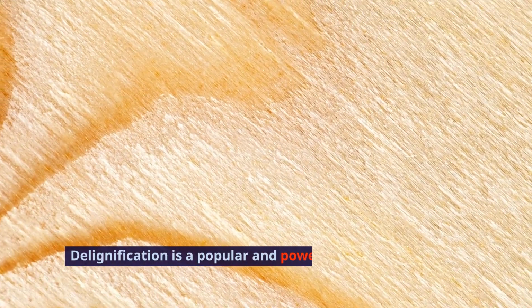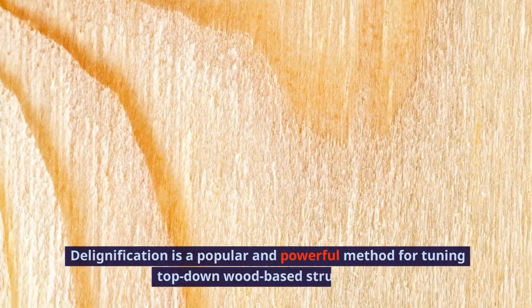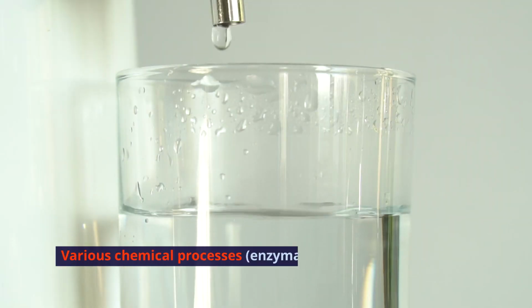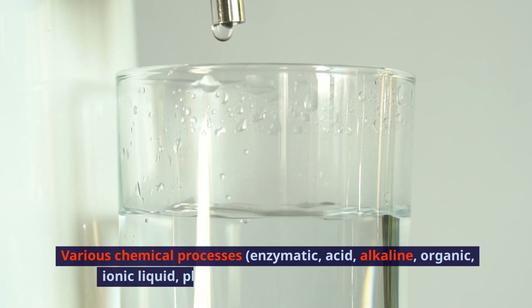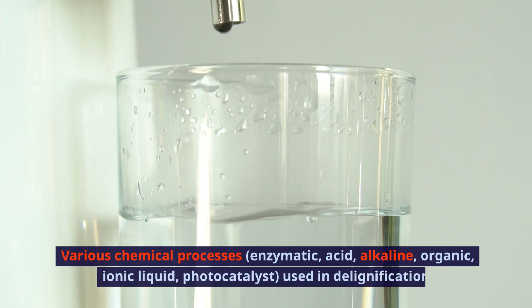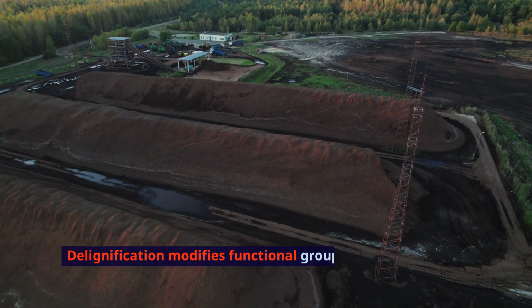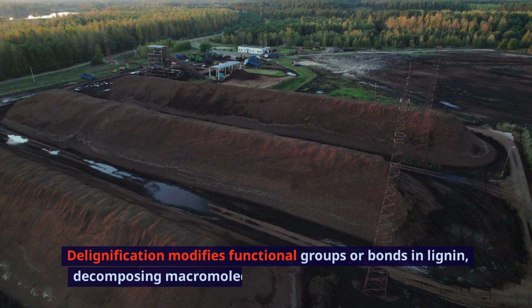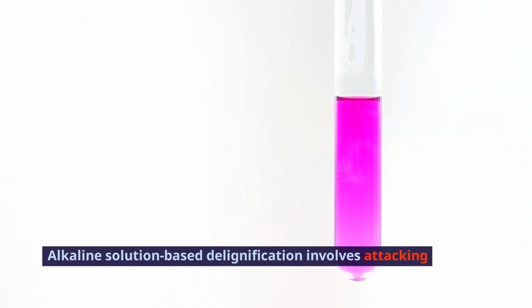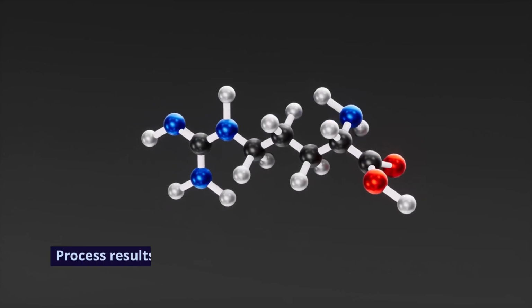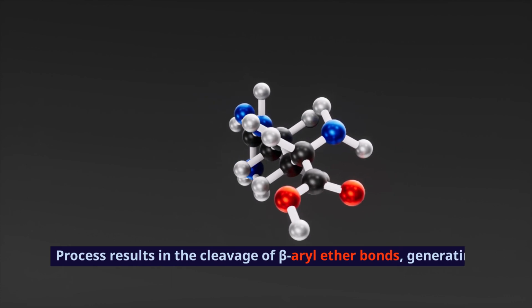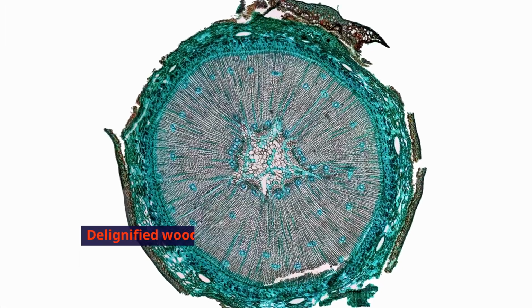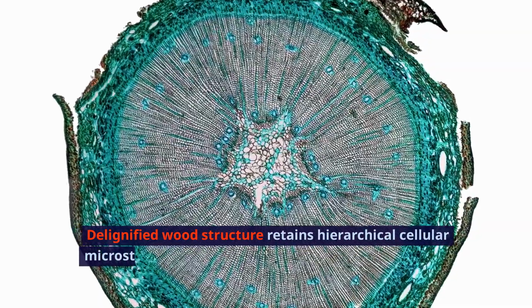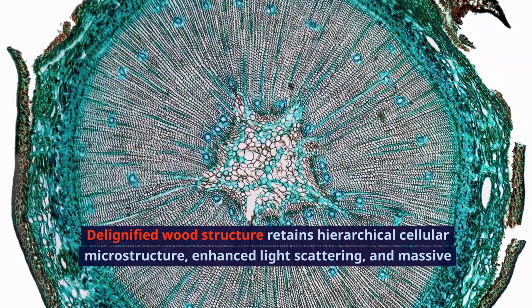Delignification as a powerful tuning method. Delignification is a popular and powerful method for tuning top-down wood-based structures. Various chemical processes: enzymatic, acid, alkaline, organic, ionic liquid, photocatalyst, are used in delignification. Delignification modifies functional groups or bonds in lignin, decomposing macromolecules for improved hydrophilicity. Effective alkaline solution-based delignification. Alkaline solution-based delignification involves attacking phenolic structures in lignin. The process results in the cleavage of β-aryl ether bonds, generating small molecular fragments. Delignified wood structure retains hierarchical cellular microstructure, enhanced light scattering, and massive nanochannels.